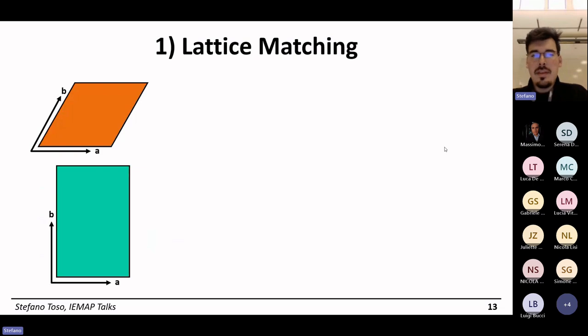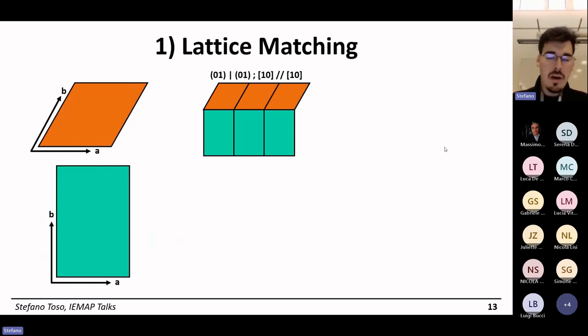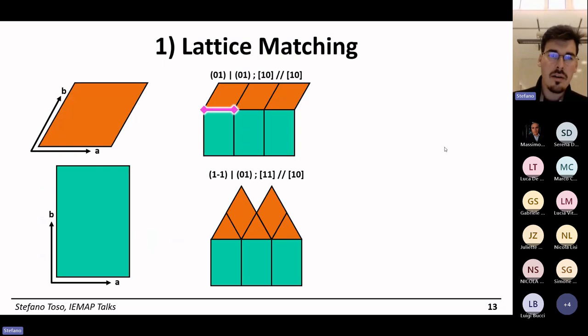In the lattice matching step, here we have a bidimensional representation. You have two unit cells of the materials, and you have to find a way to attach them to each other. One possible way is this one, and you see a periodicity at the interface that describes how the two materials crosstalk. But this is not unique. You have another one here where you tilted the orange material by some degrees, and then you have a similar periodicity at the interface, but of course the directions are different.